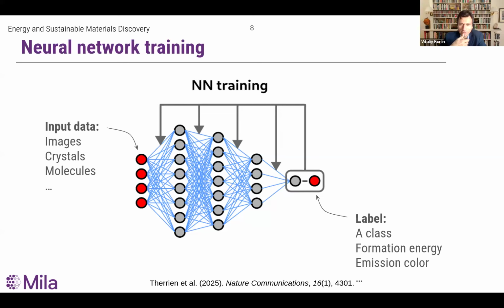And for example, when you synthesize or would like to check this property, can this formation energy be experimentally checked? Well, not directly, but you can check if a material is stable. Formation energy should give you some sort of estimate of stability, like one phase is stable versus another phase. So you can know if a phase is realized, if you have some composition and you get one phase versus another, well, the one you get most likely should have the lowest formation energy. Not necessarily, but it's a proxy for stability.